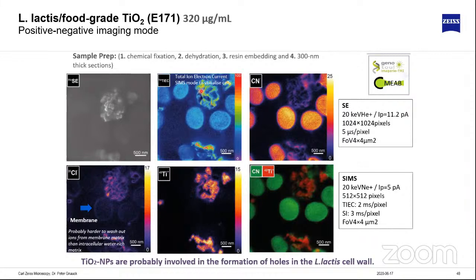And then we can look for different masses here. So if we look for the CN signal, then we can nicely see the biology that comes very nice with the CN. It's carbon and nitrogen. That's perfect. The cell membranes are typically chlorine, so we can highlight that too. And we can highlight our titanium oxide nanoparticles if we just go for the titanium signal.